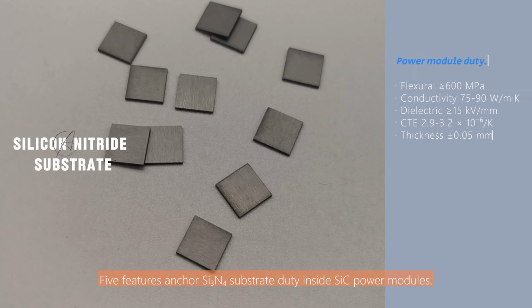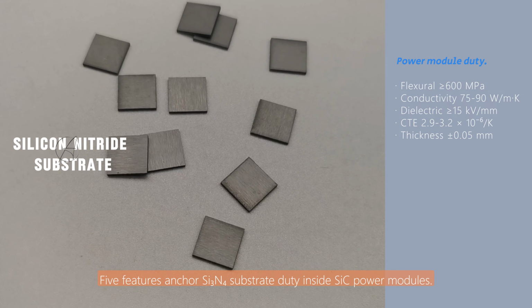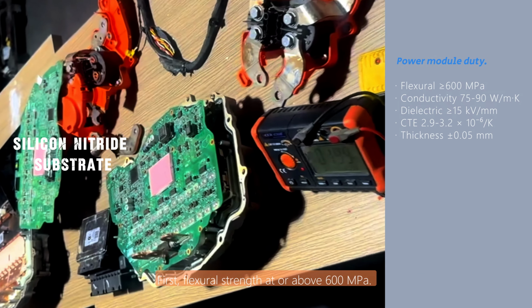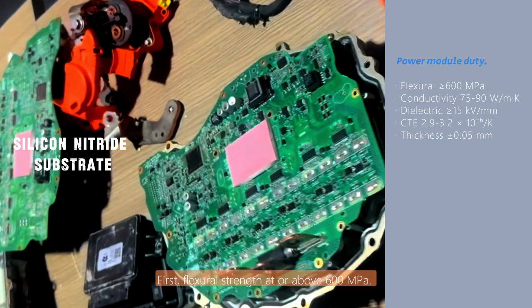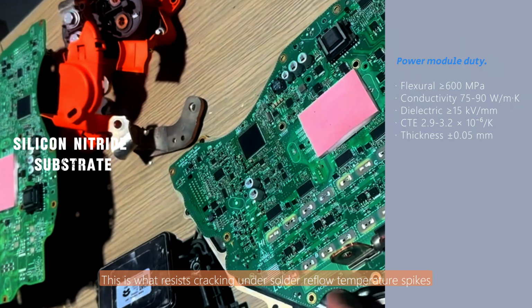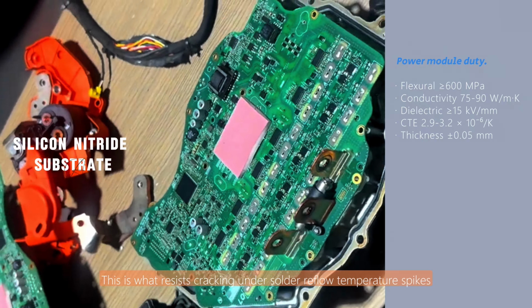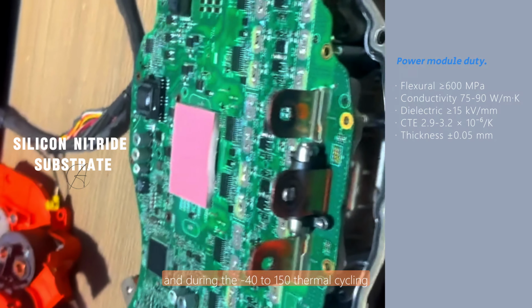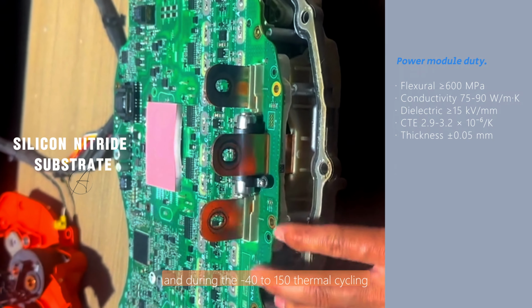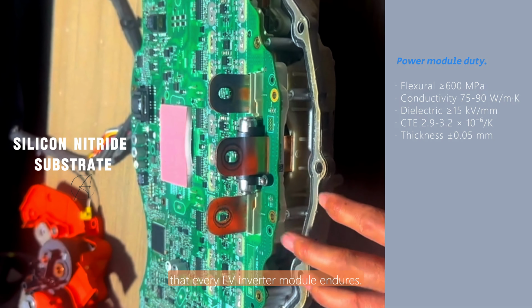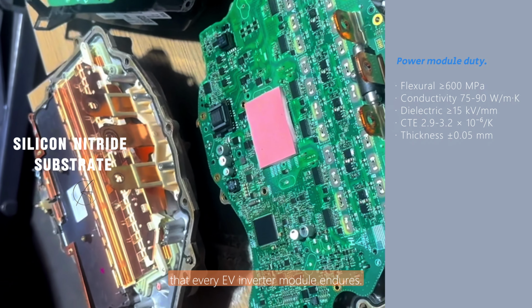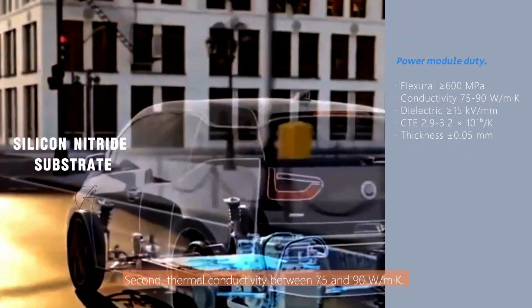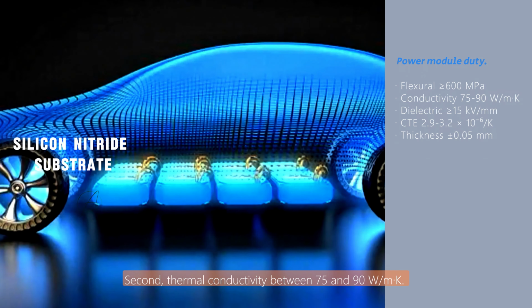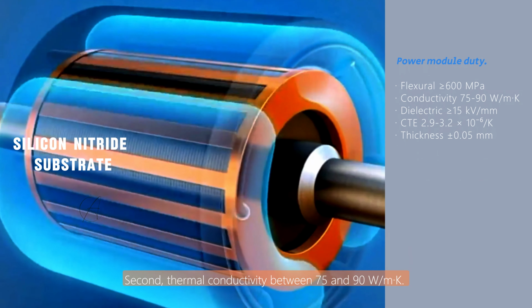5 features anchor silicon nitride substrate duty inside silicon carbide power modules. First, flexural strength at or above 600 megapascals. This is what resists cracking under solder reflow temperature spikes and during the -40 to +150 thermal cycling that every EV inverter module endures. Second, thermal conductivity between 75 and 90 watts per meter per Kelvin.